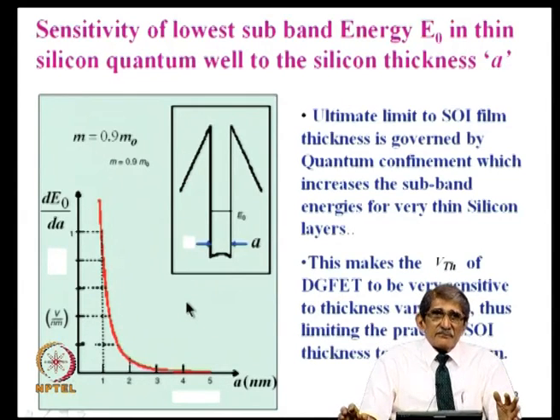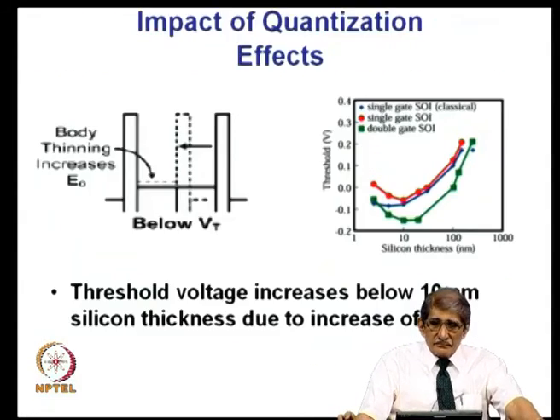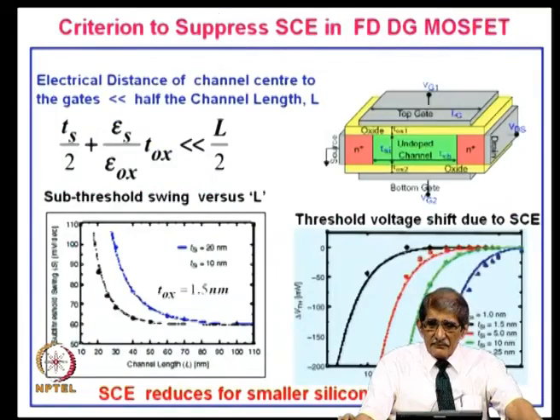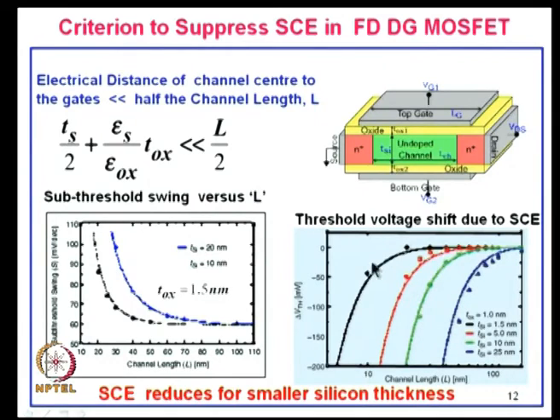So, what you are telling is, we saw in the previous slide here, we saw if you go to thinner and thinner silicon, here in this case, this was giving 1.5 nanometer. The question is, we can go to very, very small channel lengths there, but the question is whether we can really get that sort of uniformity. One way of doing that fairly uniformly is go to smart cut. Smart cut, you implant the ions exactly at the region where you want to cleave it. Okay. So, you can get about that value, but it becomes more difficult.